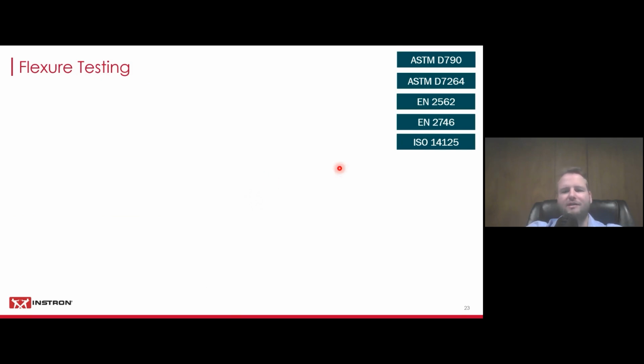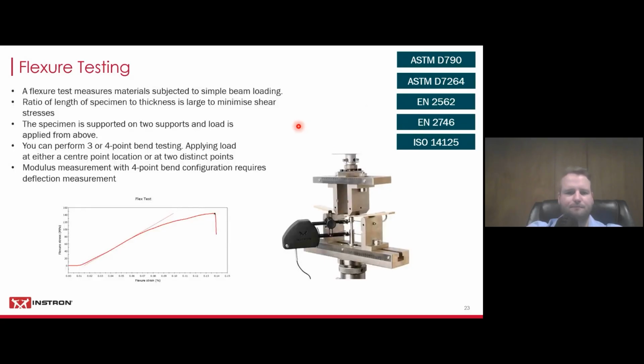Now we're going to move on to flex testing. Again, there's a huge number of testing standards that cover this, and it's like the interlaminar shear, but now we don't want shear forces. We want to minimize them as much as possible, which is why we use a different ratio of length of specimen to thickness. So we make that much larger, and you basically just use a simple beam loading technique here.